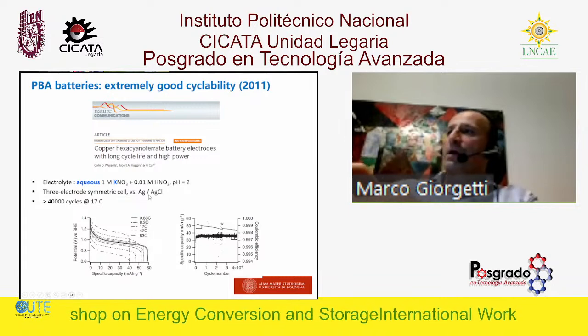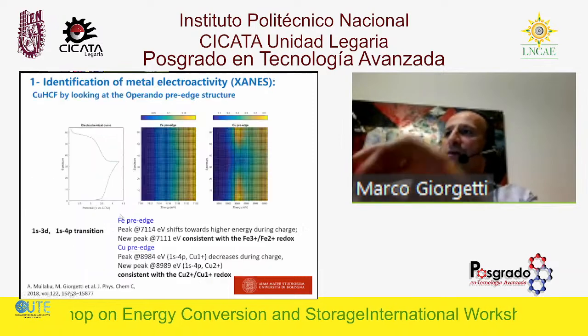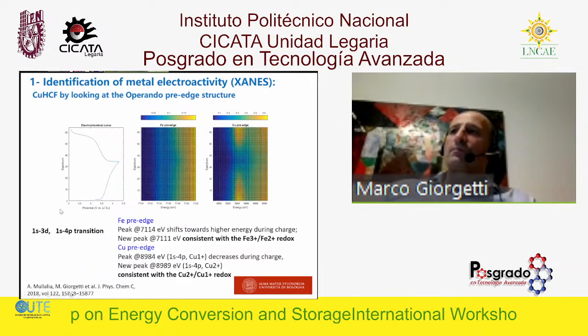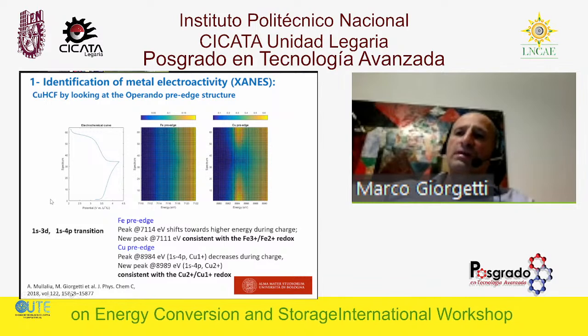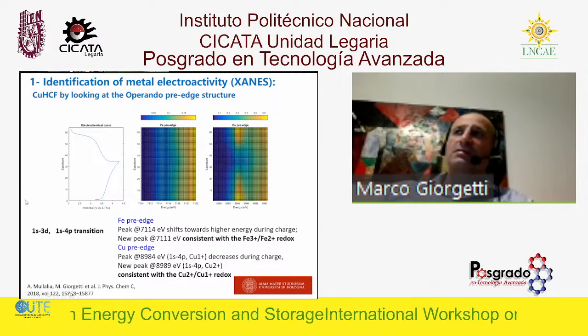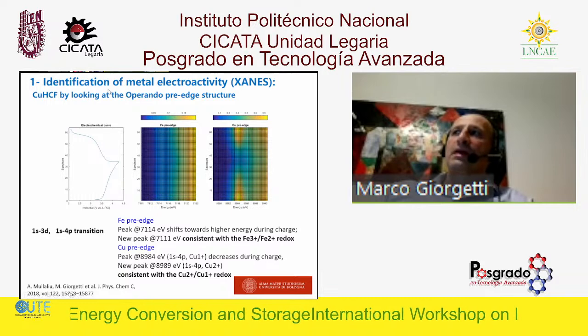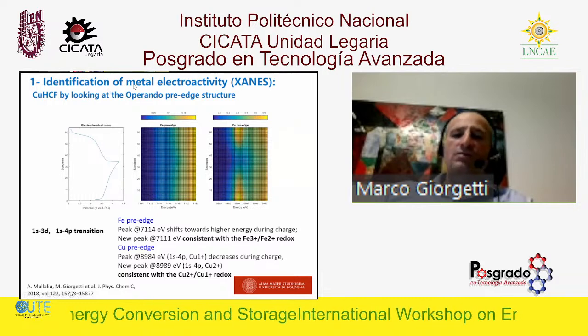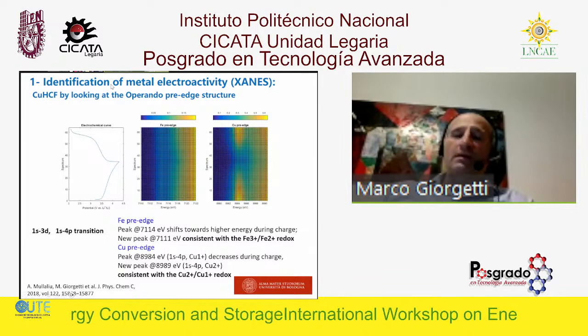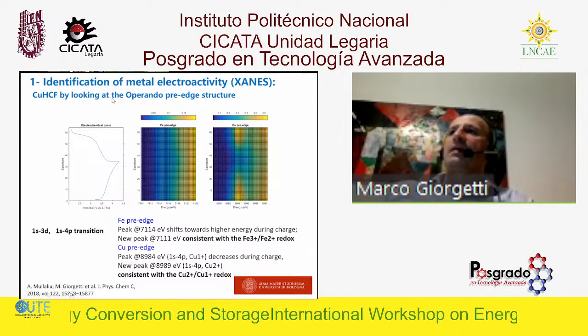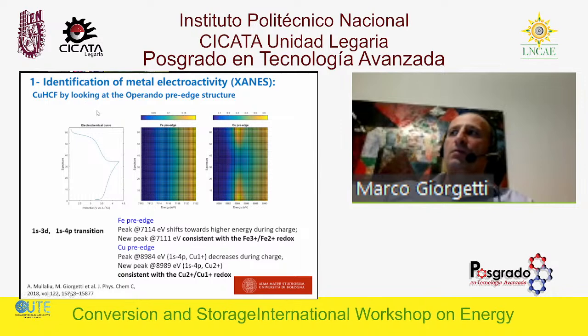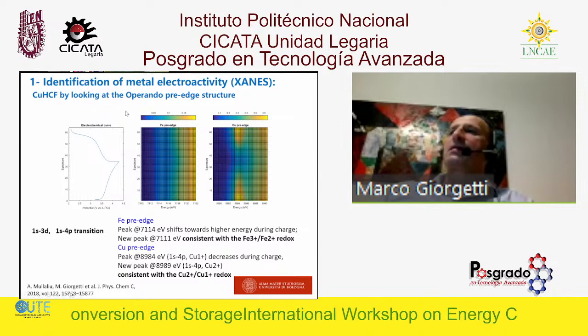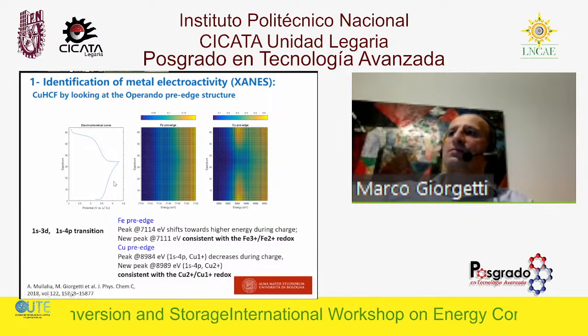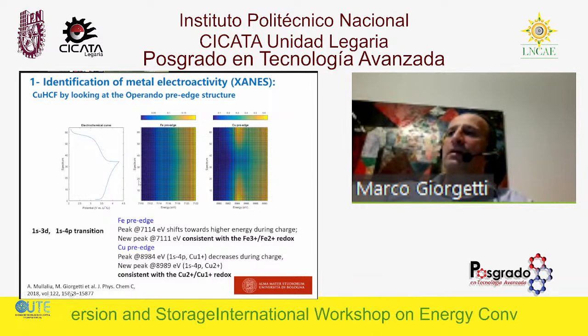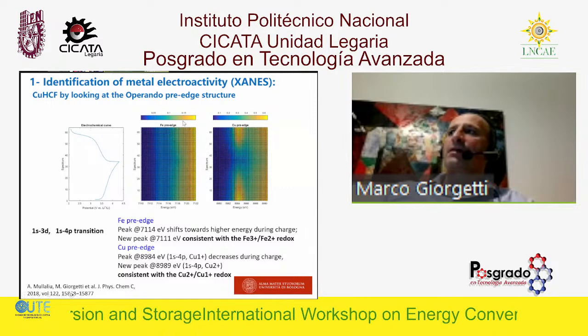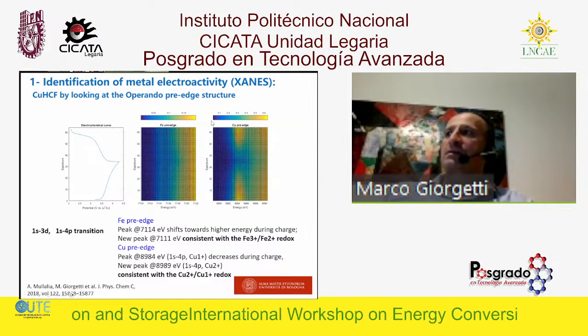So now I want to present some of the studies. The first: why do you want to use hexacyanometalates in batteries? First, because you want to do the identification of the metal electroactivity, information about the electronic structure. And the best way to do this is looking at operando pre-edge structure, for instance. Basically you conduct a charge-discharge curve, and then you monitor what you have on both sides, iron and also copper, as indicated here.